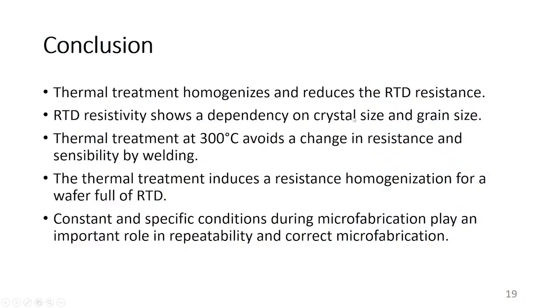Finally, as conclusions, we have some important points to highlight. One is that the thermal treatment homogenizes and reduces the RTD resistance. The other is that the RTD resistivity shows a dependency on the crystal size and grain size. Also, the thermal treatment at 300 degrees Celsius avoids a change in resistance and sensitivity by welding. The other is that the thermal treatment induces resistance homogenization for a wafer full of RTDs. And finally, constant and specific conditions during microfabrication play an important role in repeatability and correct microfabrication.